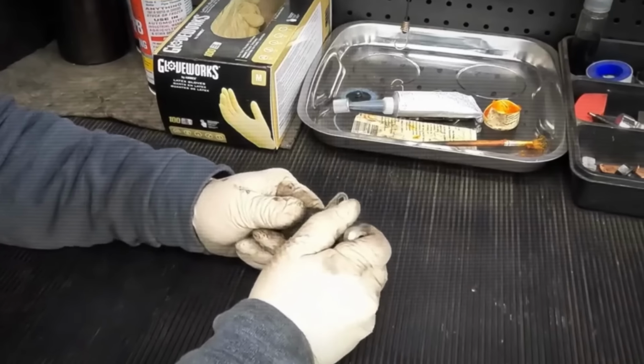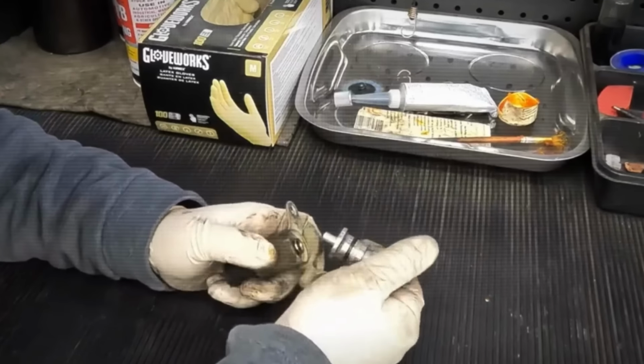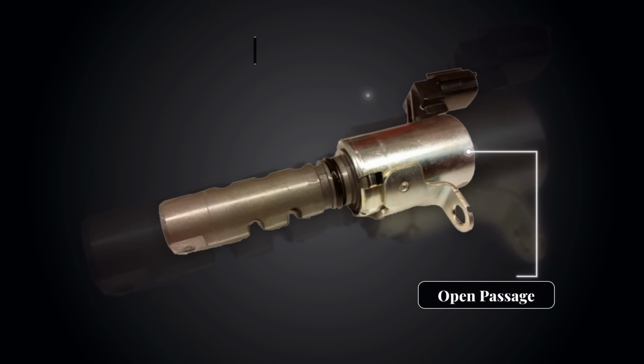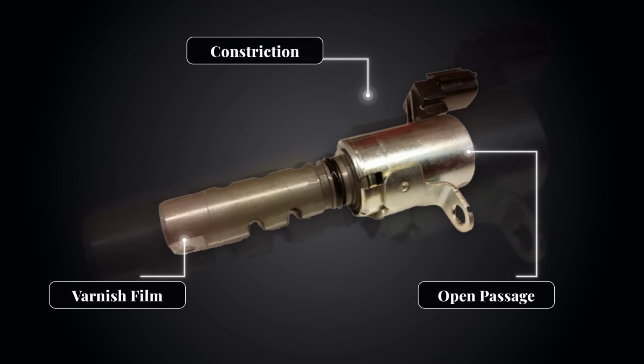When we disassembled the VVT actuator on Car A, we found a small amount of varnish buildup inside the oil control valve, the kind of thin, sticky residue that forms when oil oxidizes under heat over time. It was not enough to cause any noticeable performance issue during the 2 years of driving, but it was there. Car B's VVT actuator was essentially clean, with no visible varnish in the control passages.